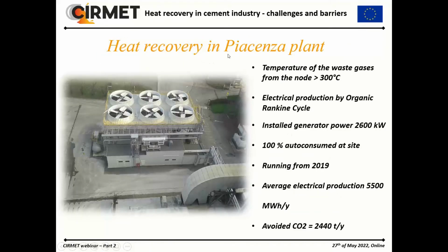Time's rush. In the Piacenza plant, our ORC is a direct cycle, so we have gases up to 350 degrees. We have installed a generator of 2,600 kilowatt. The electricity is totally auto-consumed at site, and the system is running from 2019. The average production is about 5,500 megawatt hour per year, and we avoid CO2 in the atmosphere of about 2,400 tons per year.